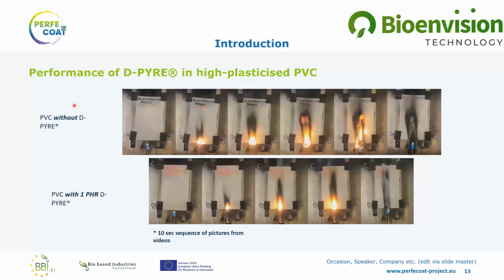And next here, we see the performance of D-PYRE in highly plasticized PVC. The top row is without D-PYRE. And as you can see, the flame height is really high, and also there is some sagging in the film. With the PVC with 1 PHR D-PYRE, you can see that the flame height is not as high, and also there is virtually no sagging, so the film retains its structure.